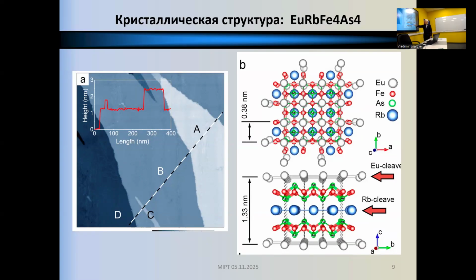So this is a picture, and this was done in Vasily's laboratory, and it consists of alternating rows of rubidium atoms and europium atoms. Rubidium has the largest atomic radius. When you cleave it for studying experimentally, you have to cleave materials for ARPES and for STM, and this cleaves most often along the rubidium, and this is quite sad because you don't have direct access to study superconductivity by STM. The tip doesn't come close to the superconducting layers.